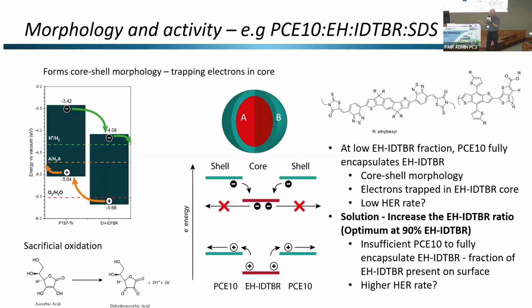And then when we look at this, this is the heterojunction of our donor and acceptor, and they were chosen deliberately to have band gaps that match the solar spectrum and a nice energetic offset in order to generate free charge carriers, electrons and holes, at the interface. So this has already been well studied in OPV, and we know that this system works. When we look at the energy levels for oxidation and reduction, we can see a couple of things that stand out here. Firstly, the energy level of our excited electrons in the acceptor should still be sufficiently offset thermodynamically in order to drive this proton to hydrogen reduction. So this is a thermodynamically favorable process.